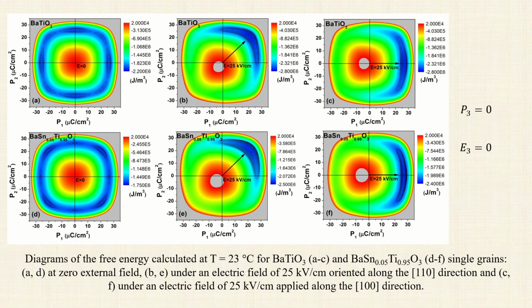The next diagrams correspond to an electric field applied along the 110 direction, which favors the minimum of energy in the orthorhombic phase, both in doped and in pure barium titanate, and to an electric field oriented along the 100 direction, which makes the tetragonal phase more stable. In fact, these diagrams show the modification of the free energy during a phase transition. In complex ceramics, all orientations of the electric fields are possible.